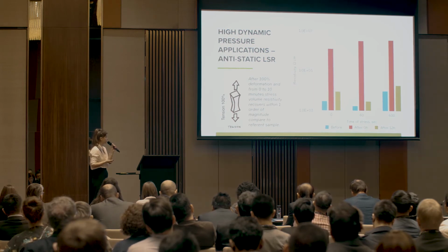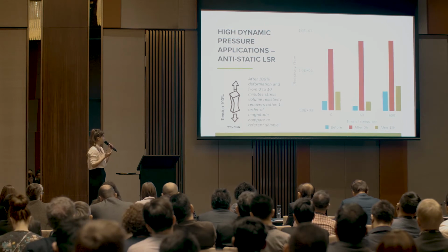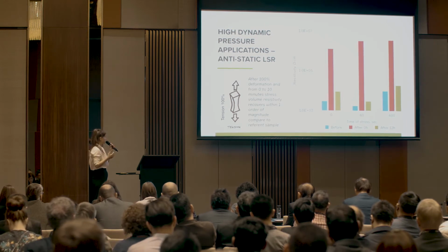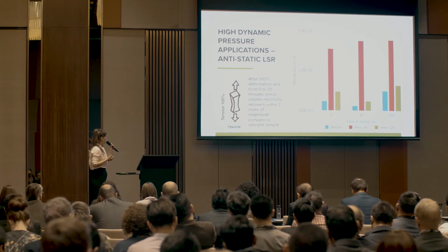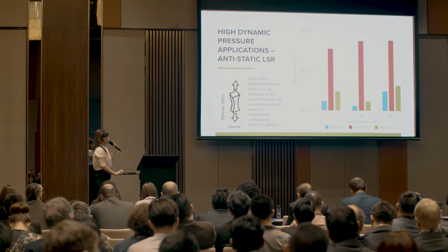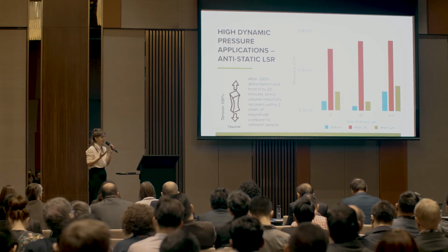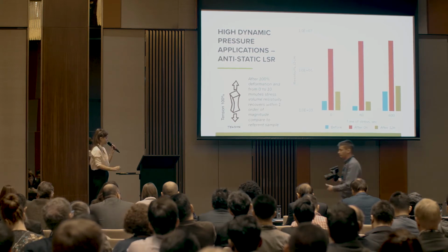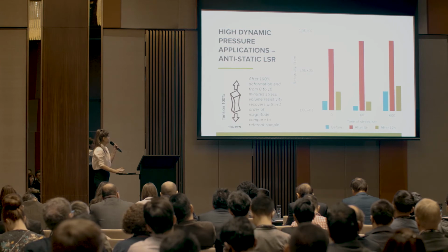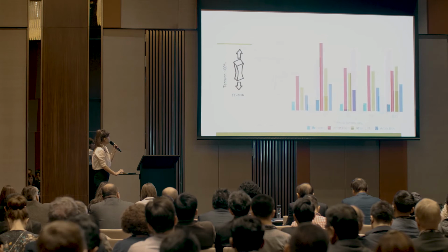there is a relaxation of the elastomer, and we could confirm that the resistance and the required antistatic level after the relaxation were confirmed at the same antistatic level. That means the material relaxes after the dynamic deformation. That is quite important in terms of the particular application and in terms of the stability of the conductive properties.